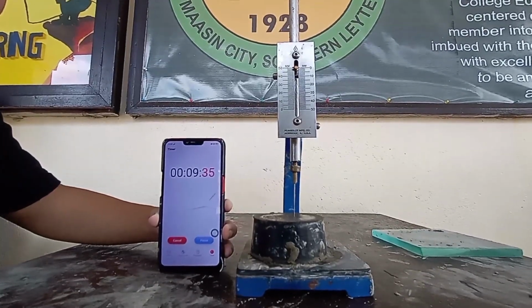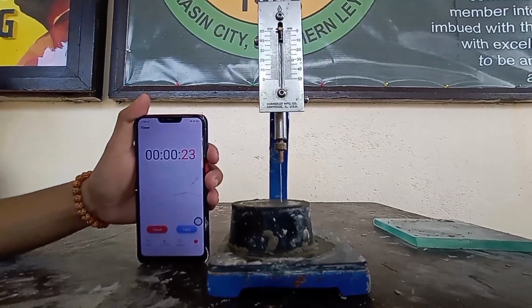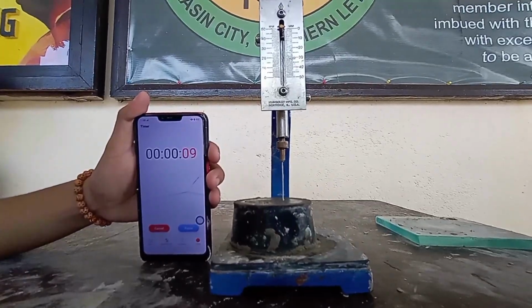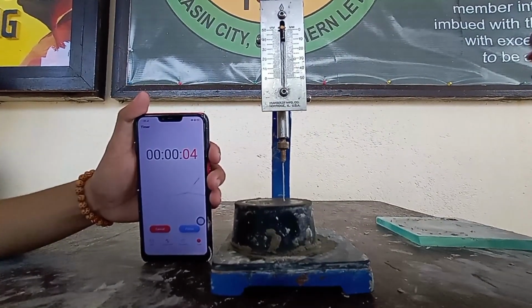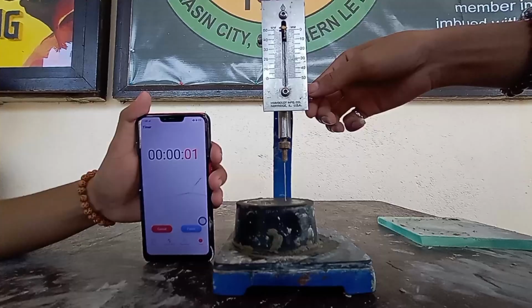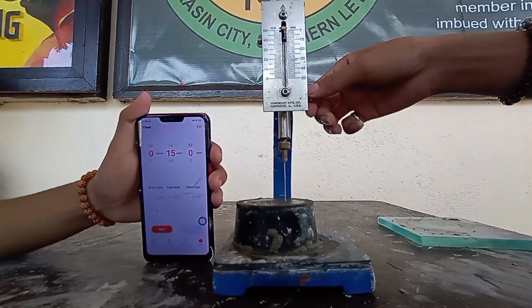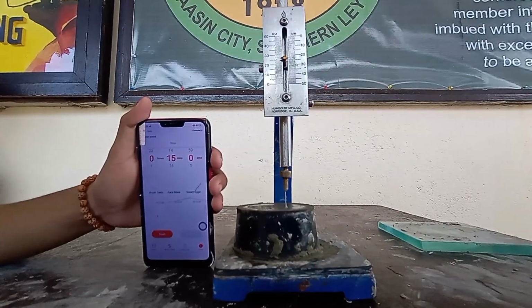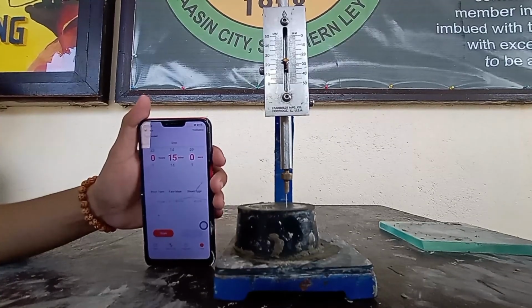Seven, record the result of all penetration tests and, by interpolation, determine the time when a penetration of 25 mm is obtained. This is the initial setting time of cement.